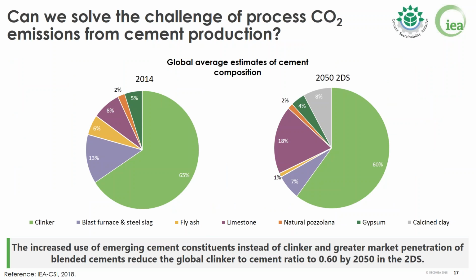reduction of clinker cement ratio. This is one of the key levers because it is expected to deliver 37% of the cumulative emission savings in 2050. According to the modeling of the roadmap, the reduction of clinker cement ratio will be from 0.65 in 2014 to 0.60 in 2050. Indeed, clinker can partially be replaced with other cement constituents, and these are mainly gypsum, natural pozzolana,